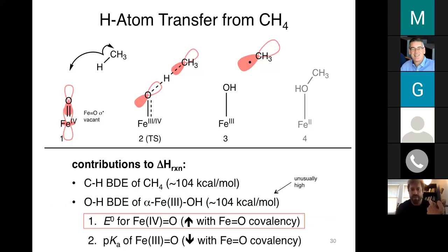So the reason that this reaction works for this particular active site comes down a lot to the strength of the OH bond of the ferric hydroxide species that you form. And this is because for this reaction to have a driving force, the strength of the OH bond that you form needs to be comparable to the strength of the CH bond that you break. So you've broken a very strong CH bond at 104 kcal per mole. So for this reaction to have a driving force, you need to form an OH bond that is also very strong, on the order of 104 kcal per mole. And for an iron(III) hydroxide site, 104 kcal per mole is much stronger than what's typical.